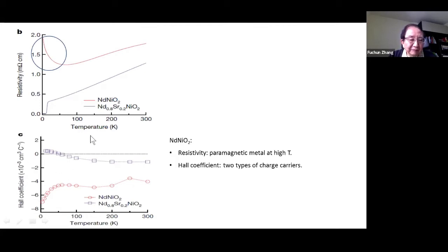The lower left panel is the Hall coefficient. Again, this red one is the parent compound, neodymium nickel O2, and the doped, superconducting one is like this. What you can see is that for the parent compound, the charge is of one type. This is negative. However, when you dope it, you have two types of charge, electrons and holes, turning around.